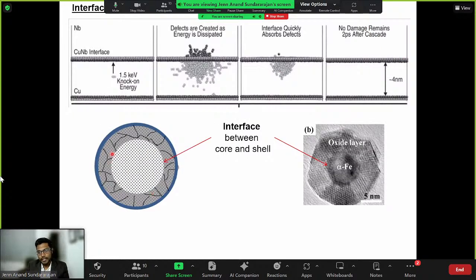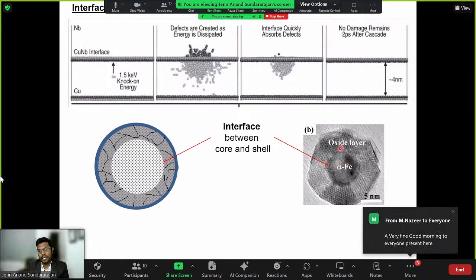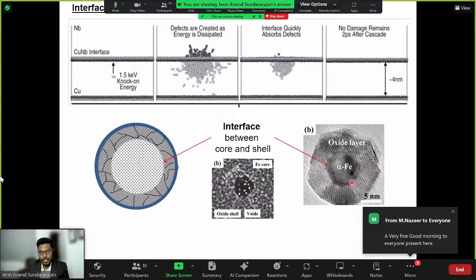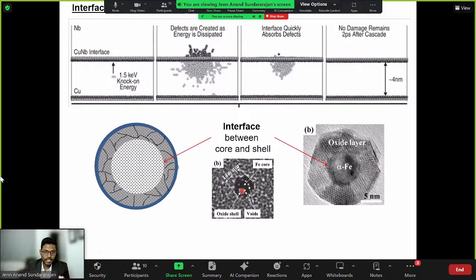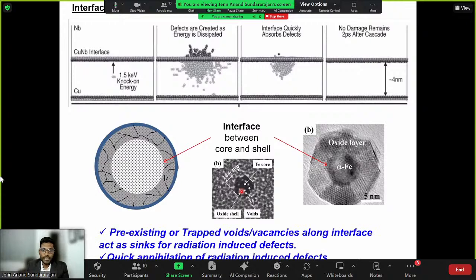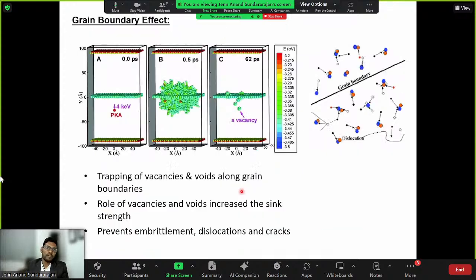As you can see, the iron core has a core and an interface, and iron oxide has an interface. That tells us these interfaces could act as a sink, because the interface always has pre-existing voids where these defects go and settle. They act as a sink. So quick annihilation of radiation defects can happen if you have interfaces and grain boundaries. That's the best way to have a radiation-tolerant material. And the grain boundary effect is the same story, because grain boundaries can act as a trap of voids and vacancies. They can even dissipate some of the dislocation loops. So grain boundaries play a huge role in minimizing radiation-induced defects.